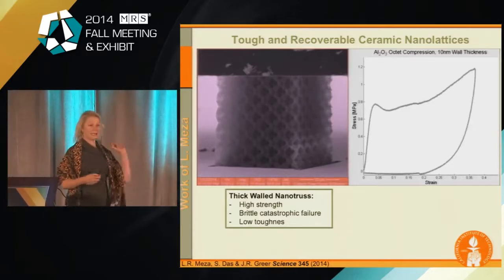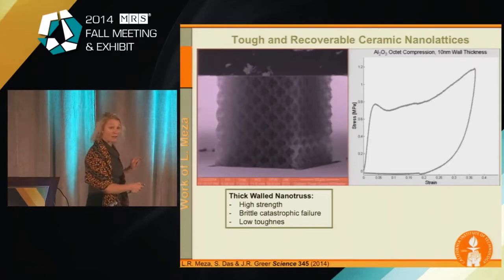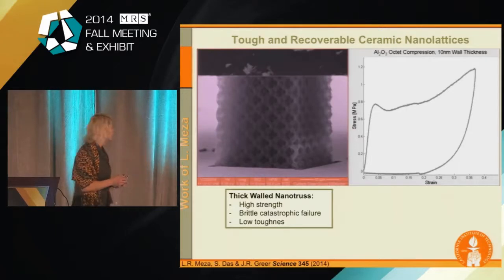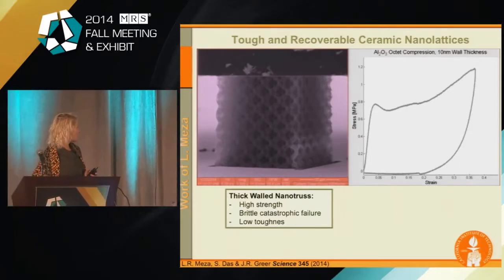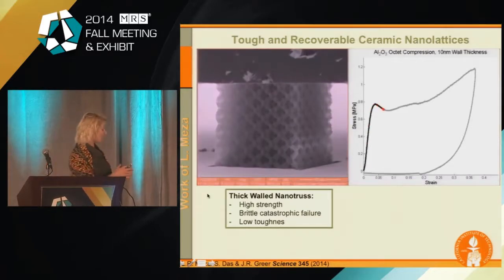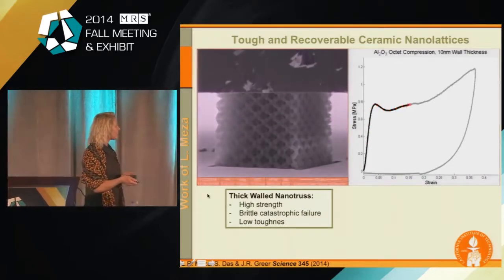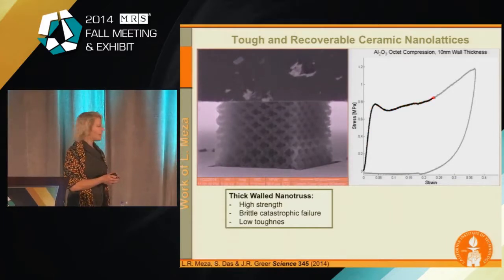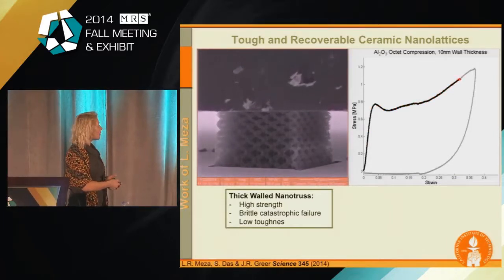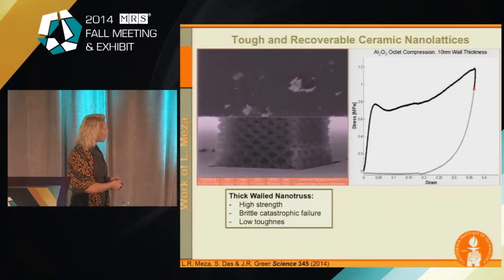We're going to repeat exactly the same experiment, but reducing the wall thickness by a factor of 5. So now our wall thickness is going to be 10 nanometers only. It was 50 nanometers, now it's going to be 10 nanometers only, and we're going to do exactly the same experiment. So here's the movie. And so we're compressing this very, very, very porous piece of chalk. And I don't know about you, but I've never seen a piece of chalk do this.